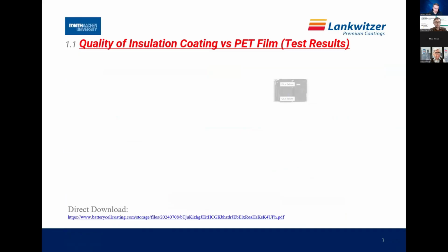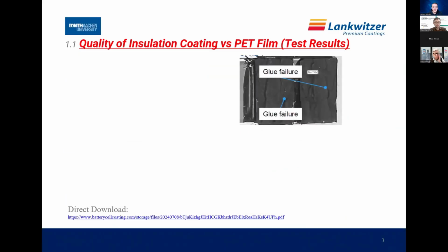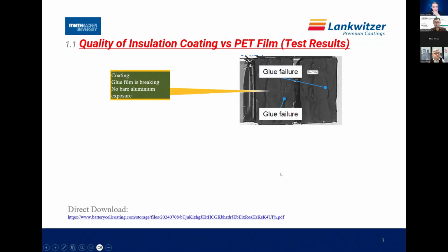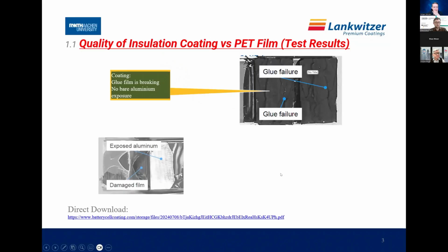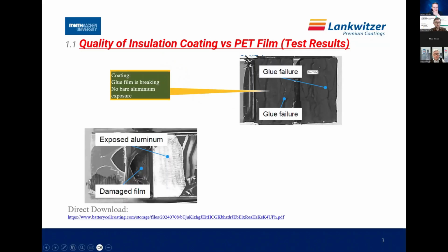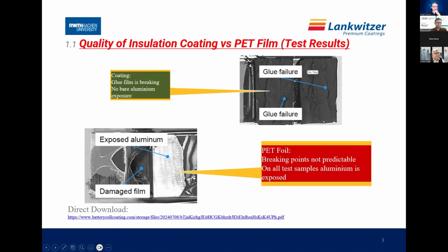And this is the main topic and the major advantage of the insulation coating. If you do a test, it's called lap shear test. You coat 2 cells together or 2 panels together and you rip them apart. And it's always the glue failing. There is never any bare aluminum underneath which comes up. If you look at the PET film, the PET film is always ripping off the battery cell and leaves bare exposed aluminum on the outside, which of course is very tricky if you have coolant, if you generate corrosion. So this battery cell will not last very long anymore.